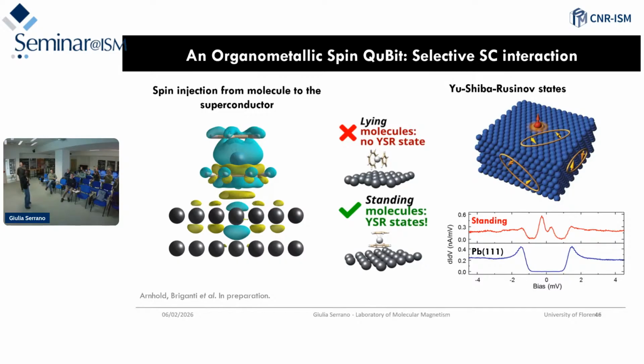For example, when you have a second layer on top of the first layer, you see an enormous difference because the second layer is decoupled, the ligand is decoupled from the substrate. Is it correct to average out everything without keeping explicitly in mind that your ligand is metallized on the surface? Have you thought about this and found that sometimes you must explain something because of the mediation of the ligand between the metal and the magnetic center, and sometimes it is not important?